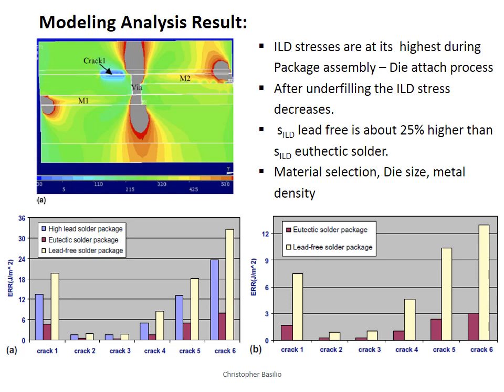It can be inferred here that the lead-free solder package has the highest energy release rate among the three types of FLI materials. On the other hand, the underfill process put the ILD stress to its lowest value. The simulation also validated that the lead-free solder bump ILD stress is about 25% higher than the eutectic solder. Finally, the study validated that material selection, die size, and metal densities affect the ILD delamination and cracking mechanism.